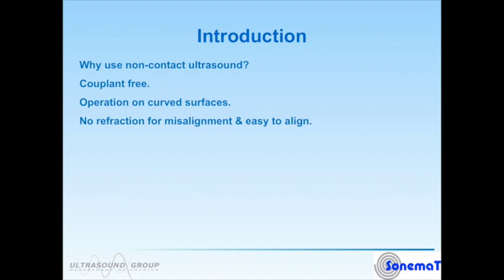The way that sound is generated using an EMAT is that there is an electromagnetic wave between the transducer and the sample surface. There is no sound wave travelling between the transducer and the sample surface. Therefore, we don't get refraction problems.